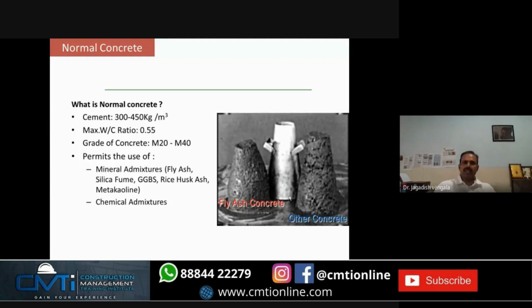And IS permits the use of both mineral and chemical admixtures. The most widely used mineral admixtures we all know, fly ash, GGBS, and then for high strength concrete applications, silica fume and metakaolin and other mineral admixtures we use in minimum quantities. Suppose if you take silica fume and metakaolin, we usually take between 5 to 15%. But in case of fly ash, we can go up to 30-35%. In case of GGBS, even one can go up to 60%.